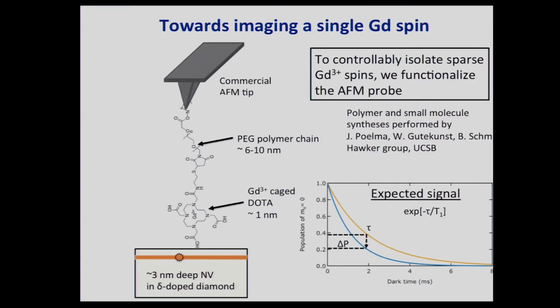So again, the goal is to image a single gadolinium spin. So we've started in this direction by working with Craig Hawker's group at UCSB, who's a chemist. What they've helped us do, or actually what they've really done for us, is to take a silicon AFM tip and functionalize it with a PEG polymer chain. You can buy these PEG polymer chains in different sizes. We bought some in the 6 to 10 nanometer size, and functionalized this AFM tip with PEG polymer chains, and each polymer chain has a single gadolinium attached to it.